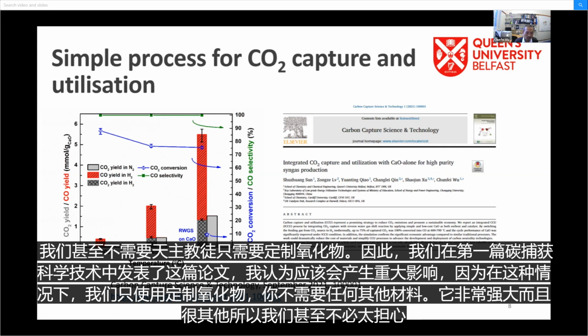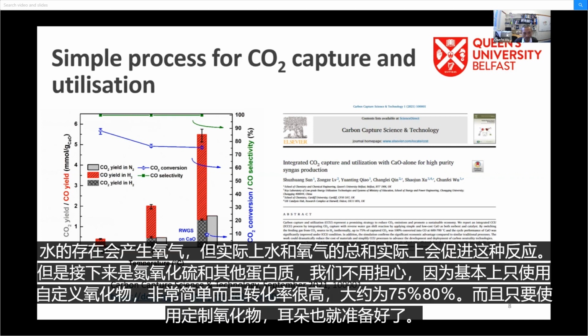And it's very robust. We don't even need to worry too much about the presence of water or oxygen; actually, the presence of water and oxygen promotes this reaction. We also don't worry about NOx, SOx, and other pollutants, because we just use calcium oxide, which is very simple. The conversion is quite high, about 75 to 80%, with just calcium oxide, and the yield is also relatively good.